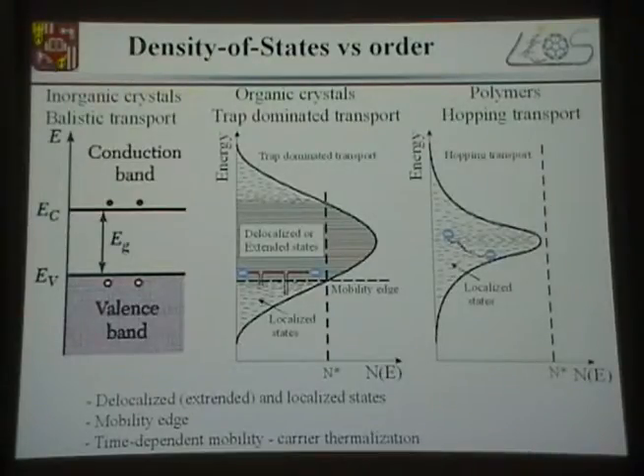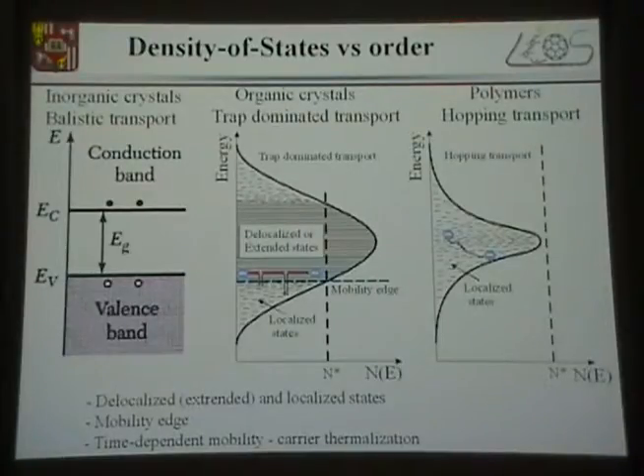And you see that the case in between, which is actually well known for amorphous and microcrystalline silicon, is that there is a combination of these two, where we have localized states and delocalized states where the electron wave functions overlap between the two states. And again, as soon as the charge carrier is present in the delocalized states, it can be transported ballistically. But what actually happens is trap-dominated charge carrier transport, where the carriers get trapped, retrapped, transported, and then trapped and retrapped again. There's also the concept introduced by Anderson, the Anderson localization, or the mobility edge, which is the energy level that separates the delocalized and localized states.